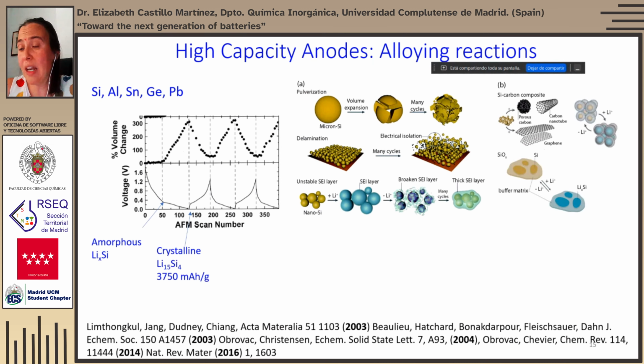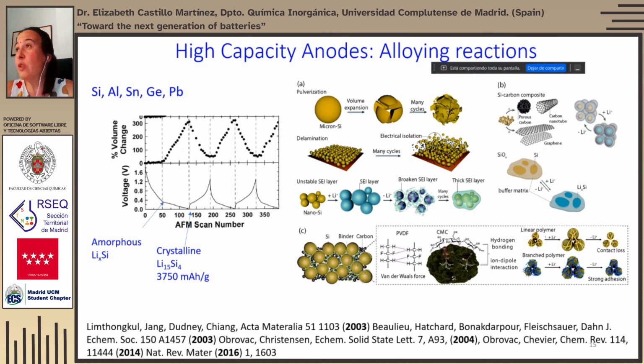Many strategies have been developed to try to overcome this, like compositing nanoparticles instead of micron size with carbon materials, putting silicon nanoparticles in a silicon oxide matrix that can buffer the volume expansion, as well as using different types of binders, which could be electronically conducting, and branched polymers, which can have a better adhesion to the silicon particle. Indeed, silicon is being used for some demonstration. I think it's not yet in the market, but many battery manufacturers are introducing, if not 100% silicon, a certain amount of silicon in their anode formulation.